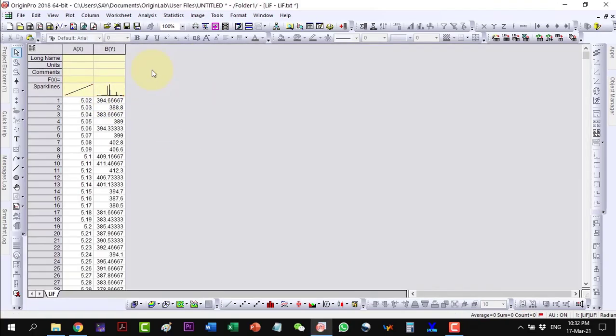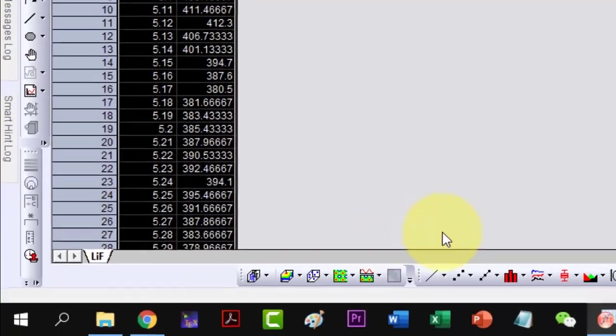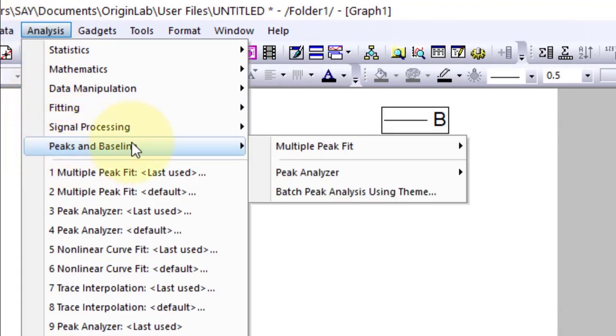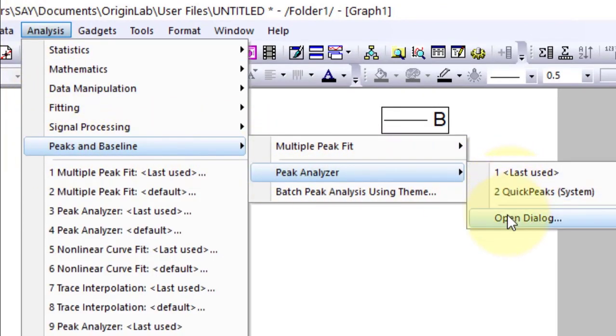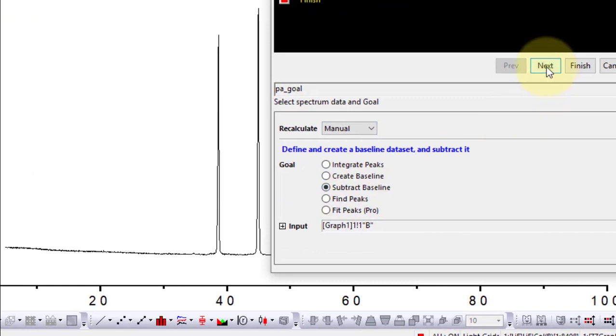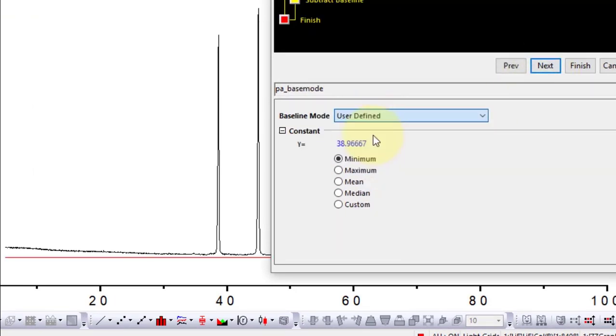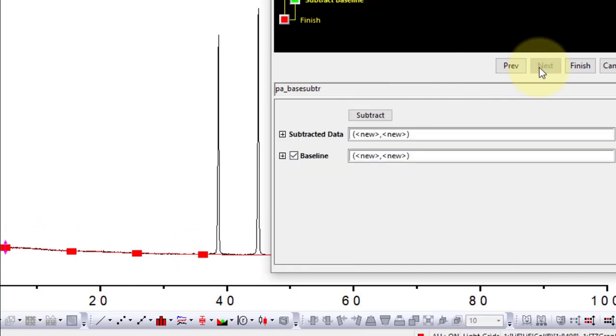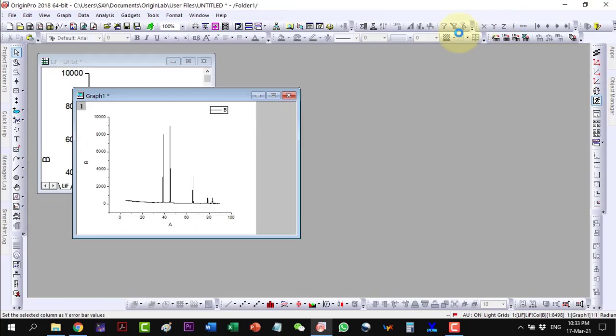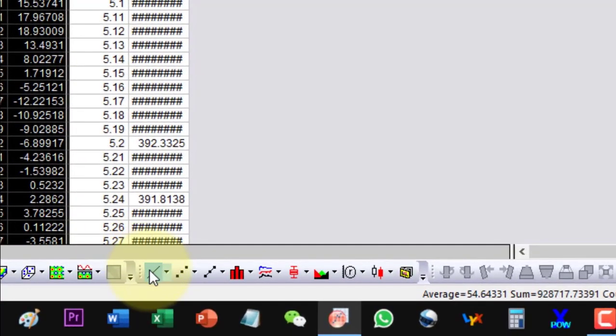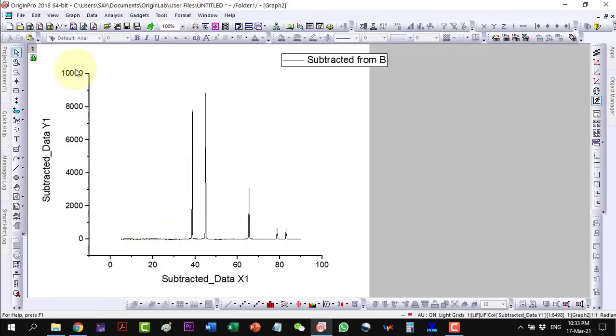Here is the data. Let me plot it. The data is displayed and I can see it needs a baseline correction. I select it and go to Analysis, Peaks and Baseline, then Peak Analyzer and open the dialog. I select Subtract Baseline, click Next, and instead of constant I use user-defined. It will give a perfect baseline correction. I click Next, Next, and Finish. It has generated the baseline-subtracted data. Let me plot it — here it is, baseline corrected now.